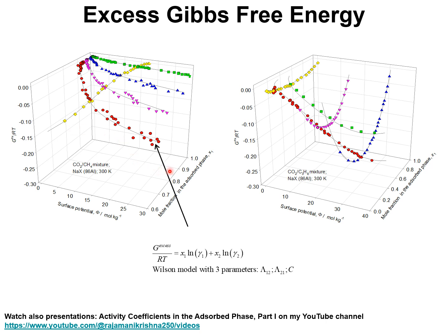The same is performed for CO2 propane mixture adsorption in NaX zeolite. In this case, a set of 5 different simulations were carried out. In 2 sets of simulations, the bulk compositions are maintained constant, and the total fugacity is varied.